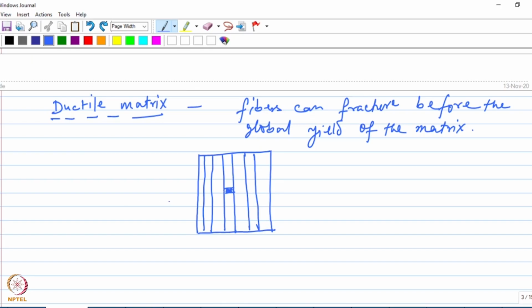Okay, so here once the fibers begin to fail, local matrix will yield at the broken fiber ends, and this yielding of the matrix at the broken ends of the fibers will relax the stresses and will prevent the crack from propagating to the adjacent fibers. Okay, so what we are saying is once the matrix yielding starts, it will basically lead to stress relaxation, and this will have a blunting effect on the crack tip, right? So here at the end of the fibers, at the broken end, it will basically relax the stress and blunt the crack.